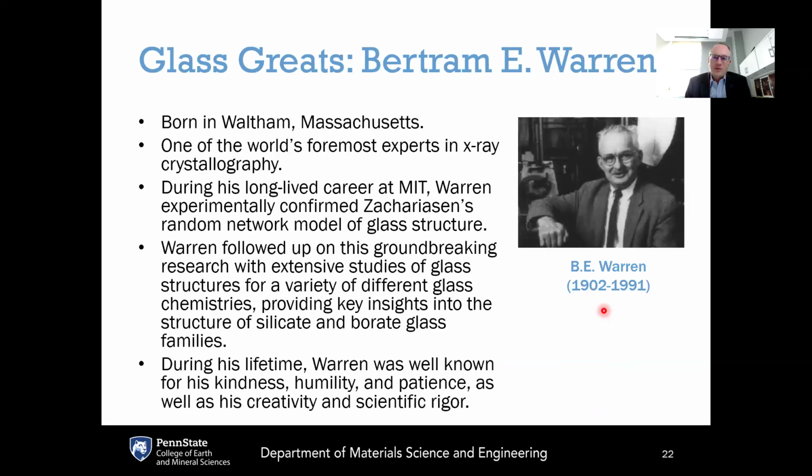And this is one of the really interesting things that we're going to come back to in the next lecture when we deal with borosilicate and boroaluminosilicate glasses: the same modifiers can play different structural roles depending upon which network formers are there. I'm going to return to this next time when we cover boroaluminosilicate glasses, where we will see that the same network modifier, sodium, can have 3 very different structural roles depending upon whether the sodium associates itself with a silica, a boron cation, or with an aluminate unit.